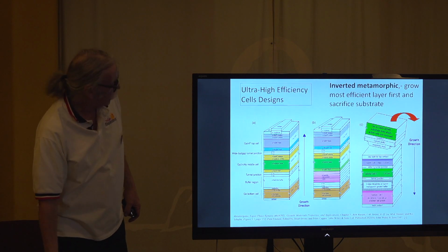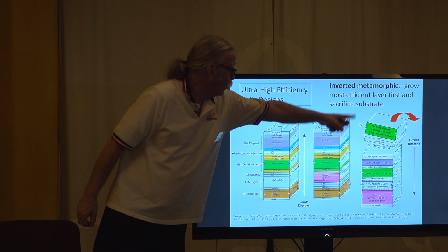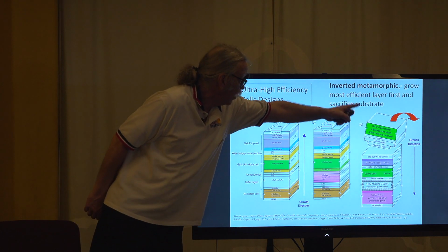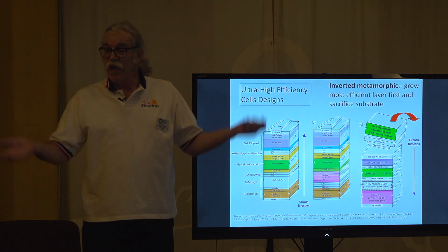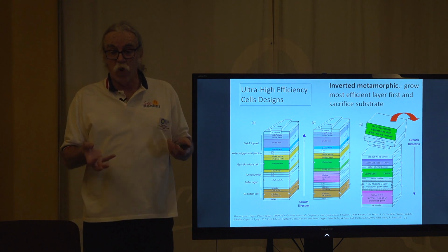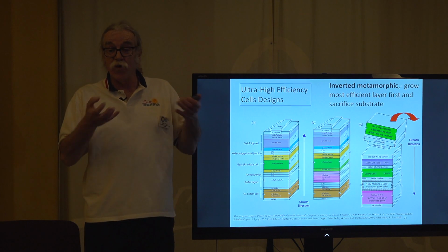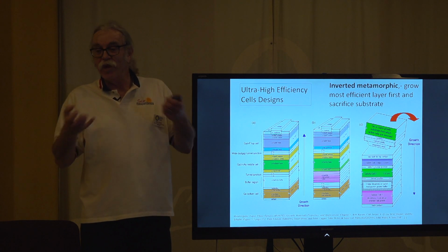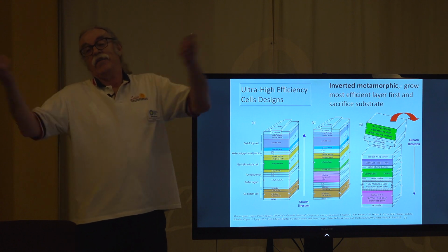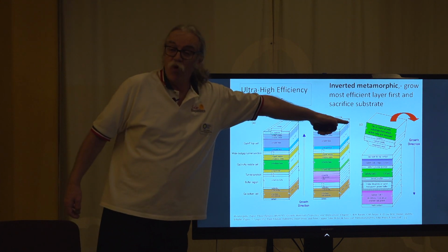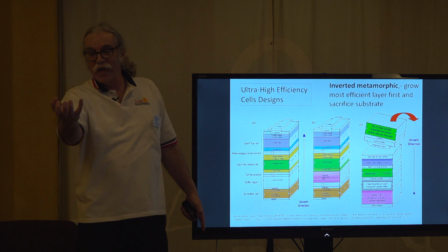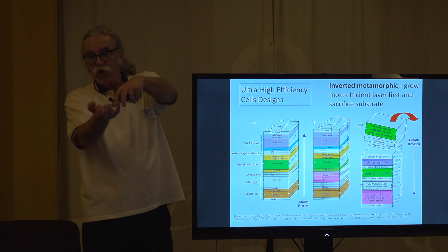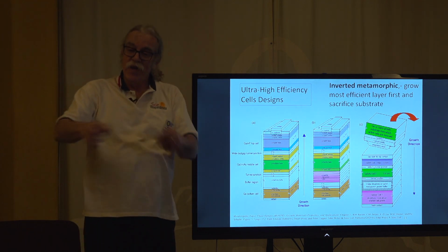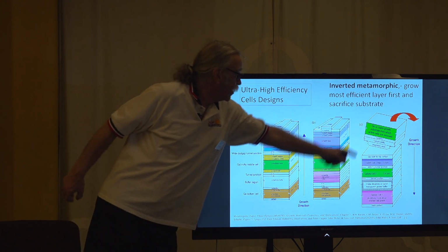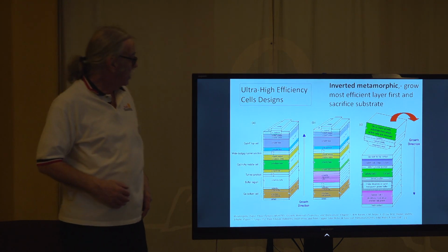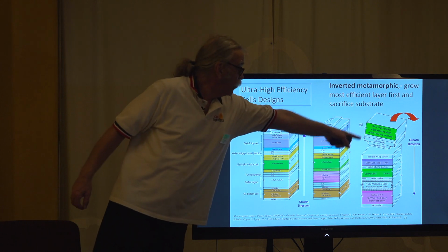They're all designed by computer models. So this is even some more. I said the inverted metamorphic, that's this one. They realize that, hey, on these high efficiency cells, if I grow the most important layer, the one that generates the most power, first, I'll get more power. It'll be better. Why haven't I done that before? Because it means you have to throw away what you grew it on. You grow it on a wafer, you've got to remove the wafer. So you grow this film, and you've got to etch away the entire wafer and leave your little film. And that's what that is. But those are the highest efficiency technologies. And they're very radiation resistant.